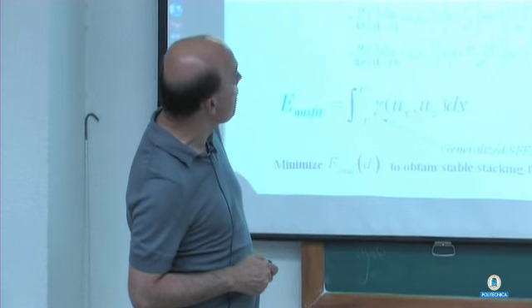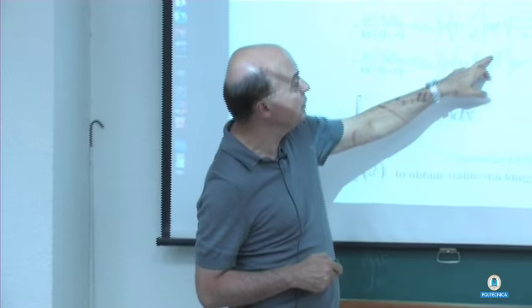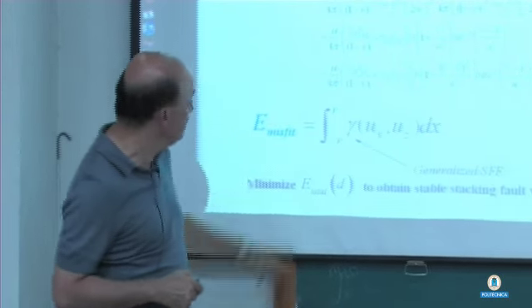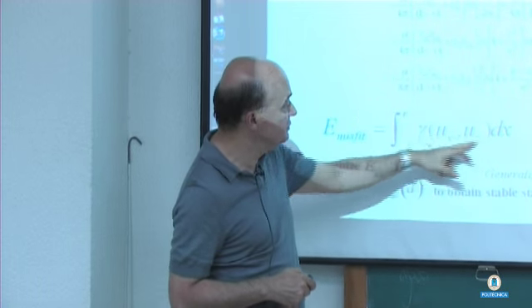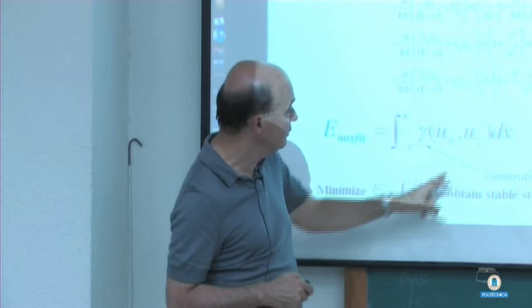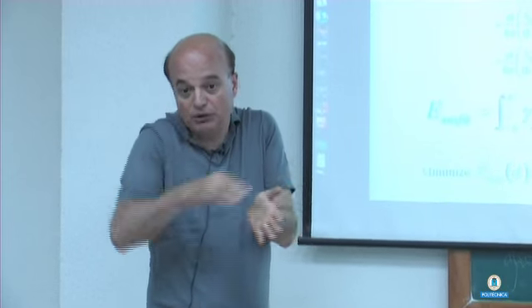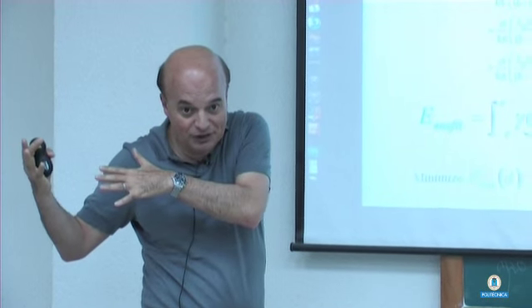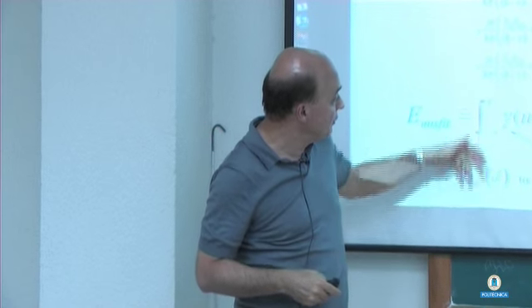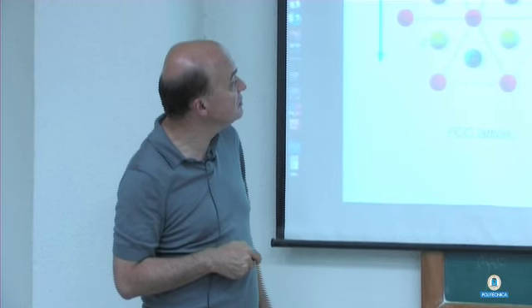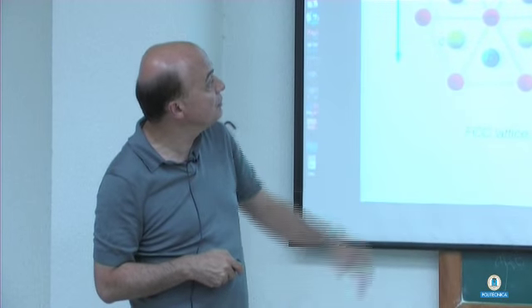And D appears in my equations here. And then the misfit energy is again the integration of the gamma curve. But now there's no twin. You don't have to go through the entire three-layer twin formation. You're just going only to formation of the intrinsic stacking fault. You again minimize this E. It's the same figure I showed before.